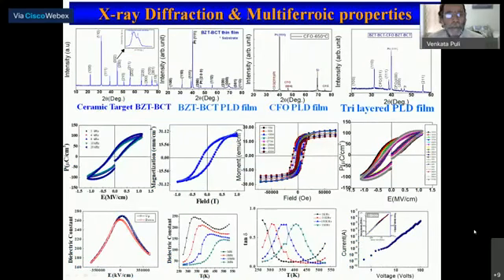We got excellent room temperature phase properties for all the individual films as well as for the combination of tri-layers. Then we measured the ferroelectric and ferromagnetic properties at room temperature at different frequencies. To check the thermal stability of these films, we made both ferroelectric and ferromagnetic measurements from low temperatures to high temperatures, until the phase changes from ferroelectric to paraelectric in the case of ferroelectric materials, as well as the TC of ferromagnetic materials. The thermal stability was also examined using the dielectric properties, where these materials have shown very low losses and low leakage current behavior.